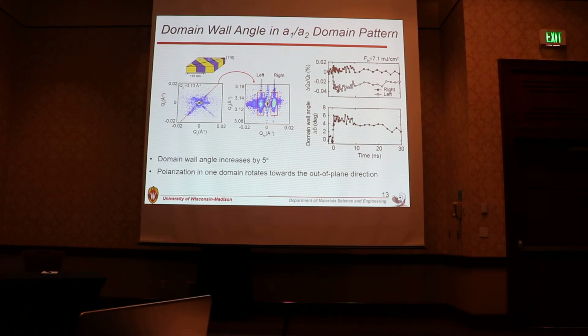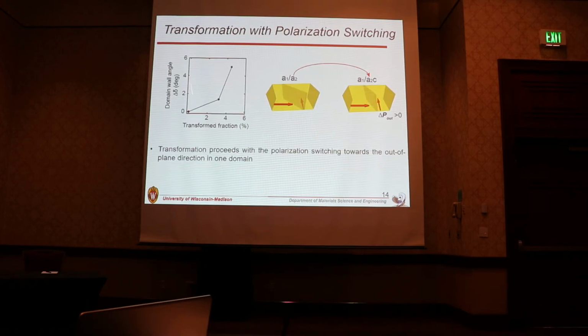It's quite a big number. And we measured the domain wall angle changes as a function of transform fractions and found that with increasing transform regions, the domain wall angle changes increase too. And what we can suggest here is that because the domain wall angle changes, the polarization in one domain should experience polarization switching toward the out-of-plane direction. So A1, A2 domain patterns should be transformed to the A1, A2C domain patterns. I think it's an intermediate pattern before becoming the AC domain patterns. So from this, we can understand that domain pattern transformation proceeds with the polarization switching in one domain.